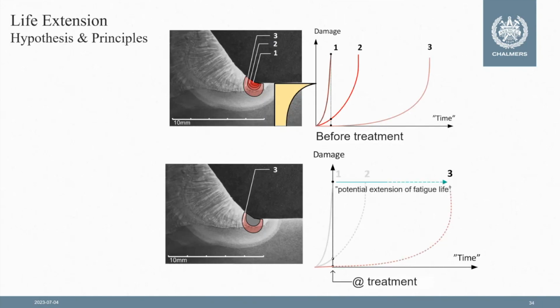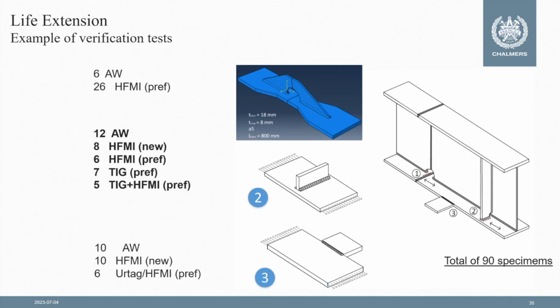The principle, or the hypothesis for this method, comes from the idea that fatigue damage is very localized at the weld toe, as I mentioned before. And during the service life of the welded detail or of the bridge, fatigue will accumulate, assuming now that we don't have any cracks initiating in this region. If at any period we come and do the HFMI treatment on this detail, we will presumably be able to erase the fatigue damage that has been accumulated, and this way extend the fatigue life or give the bridge a new fatigue life in principle. And this is something that has been investigated both by our research group here at Chalmers, but also by other colleagues in various locations.